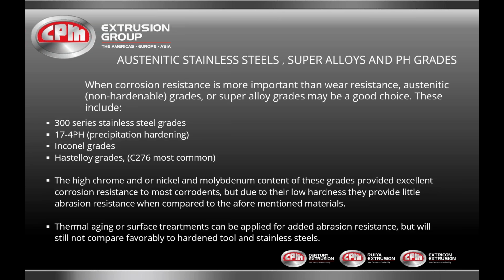The austenitic stainless steels, the superalloys, and the pH grades: if corrosion resistance is more important than wear resistance, austenitic or non-hardening grades may be the solution you're looking for. In some cases, precipitation hardening grades or one of the superalloys might be a good option. These include the 300 series stainless for austenitic and 17-4 PH for the precipitation hardening, and the Inconels and Hastelloys belong in the superalloy group, also known as high temp alloys. The high chrome and nickel, along with the molybdenum content of these steels, offer excellent corrosion resistance to most corrodants.